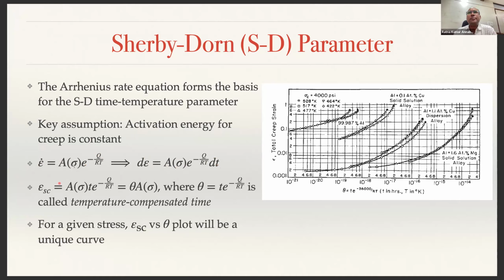And then for the steady state creep rate, if you integrate that, you will get theta equal to t e power minus Q by RT. And this is what we call temperature compensated time. And that is what we are plotting on the x-axis. So for a given epsilon SC versus theta plot, you will get a unique curve for each material. You can see this is a unique curve for 99.987% aluminum. This is a unique curve for a different aluminum. This is a unique curve for a particular aluminum alloy.